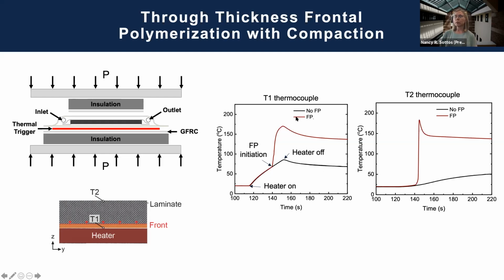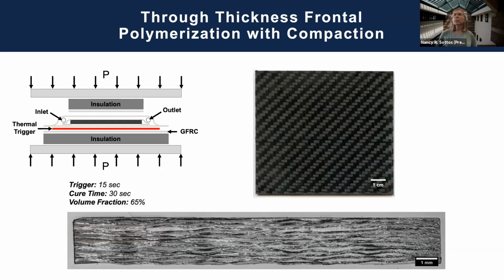But you can see what happens when there is frontal polymerization. It's heating, and then all of a sudden we have that trigger where the exotherm kicks in, and you can see that very nicely here. And then, this is just the temperature at the bottom of the laminate. At the top, you can see this nice front that is propagating and moving through the material. And this through thickness technique with the compaction leads to some very nice materials. We can have very short trigger times and short cure times, again, about 30 seconds, and very high volume fractions, so 65% volume fraction, as I mentioned before.